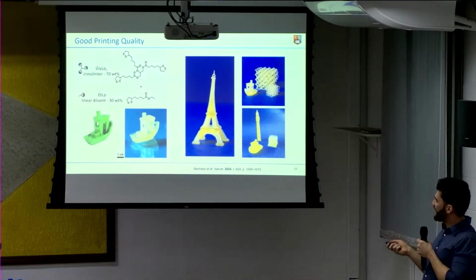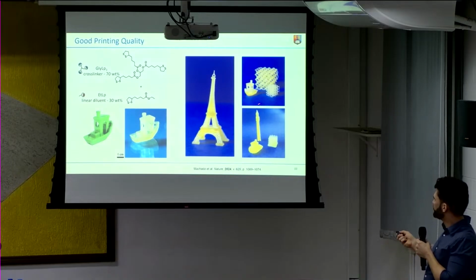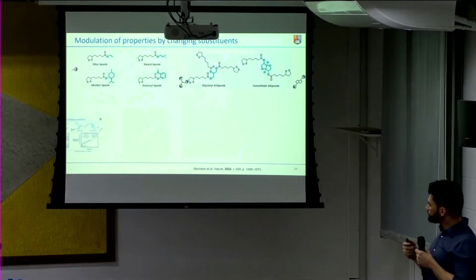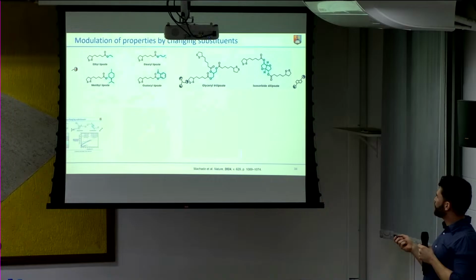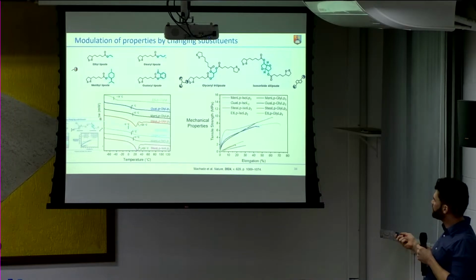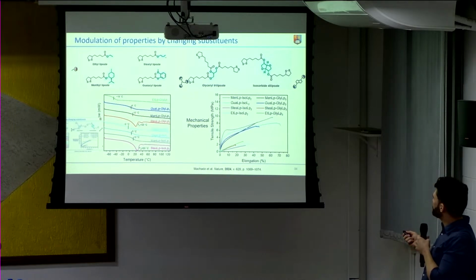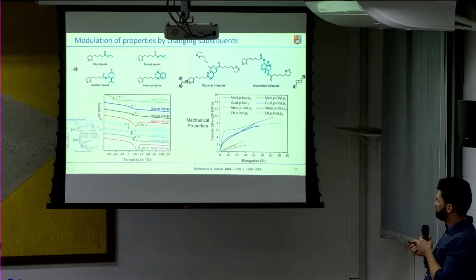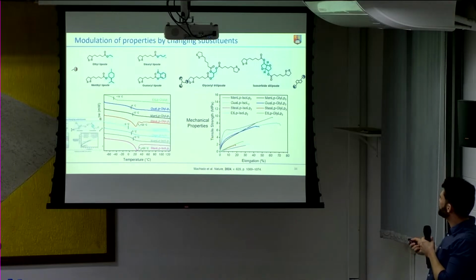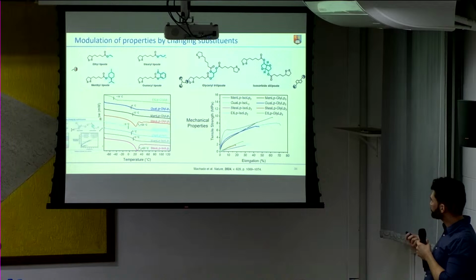And then we started printing more complex structures like the Benchy boat, Eiffel Tower, some scaffolds, the Old Joe from the University of Birmingham. Later on, we tried modulating the properties, changing the substituents here. When we have some cyclic linear monomers, we can see the increase in the glass transition temperature. The same happens for the cyclic crosslinker. When we have the long alkyl chain in the linear monomer, we have some crystallinity in the material. And of course, that also affects the mechanical properties. So stronger materials with cyclic moieties, weaker materials with linear moieties. So we can get a full range of different materials by changing the alcohols.